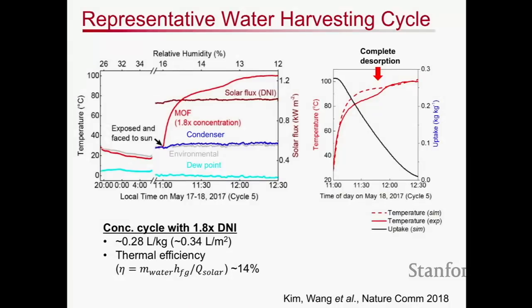We've taken data monitoring the temperature as a function of time for the case when we're first adsorbing and then desorbing once we expose it to the sunlight. Because we're still dealing with relatively small quantities of this metal organic framework, we weren't able to actually capture the amount of water from the surface. And so we've been able to take advantage of simulations to help us quantify the amount of water we've been able to capture.